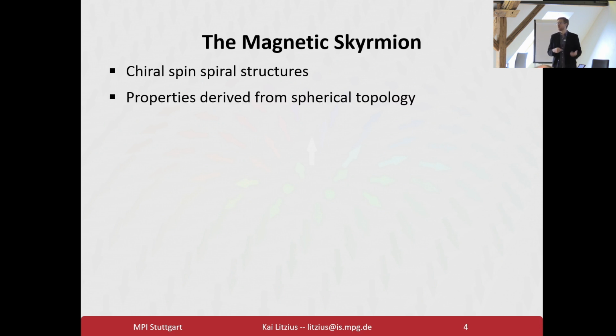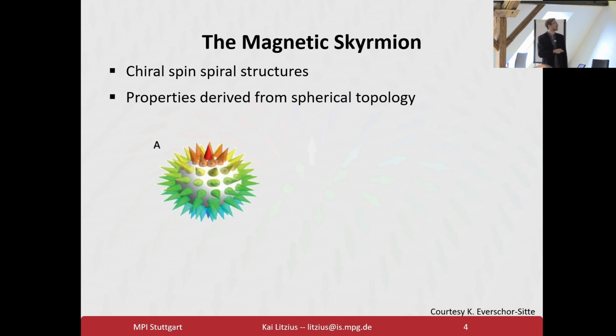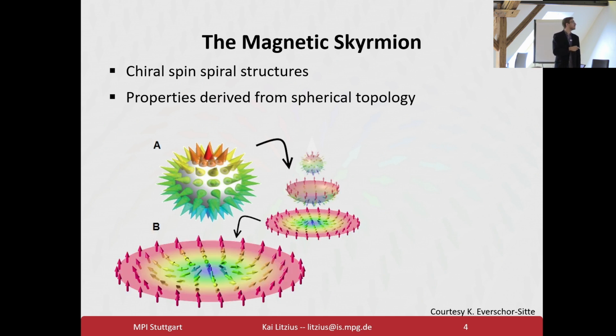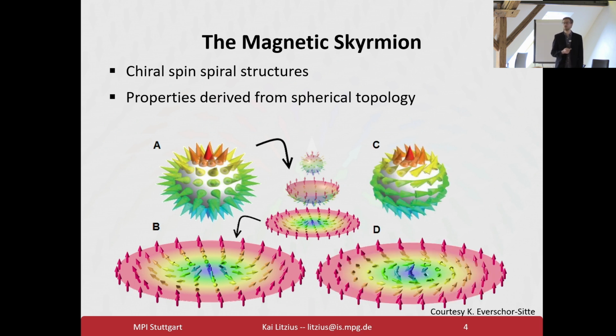You've heard that already a couple of times, so I'll keep it brief. They're chiral spin structures, as Berger pointed out, and they have this special topology which derives from a sphere by putting spins on the sphere. You can imagine that as you project the sphere down into a plane by opening it up at one pole. For example, here you open it up at the North Pole so that the background becomes the North Pole orientation, up in this case, and your South Pole becomes the down orientation and is the core of the skyrmion. Now the orientation on the sphere defines the domain wall, which means you can also generate a second type of skyrmion by combing spins around the sphere, and you end up with a different in-plane orientation of the domain wall. This is called a Néel skyrmion on the left and a Bloch skyrmion on the right, depending on the orientation of the wall.